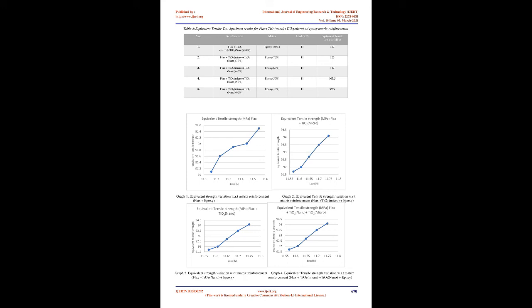From the above outcomes we can see that the highest tensile strength is obtained at Flax plus TiO2 micro plus TiO2 nano, 20%, and epoxy, 80%, composition. Concluding remarks. The tensile strength of all 6 samples was evaluated and test results of all samples are shown in the table. It was discovered that sample 1 has the lowest ultimate tensile strength when compared with the remaining samples. Then after there was a tremendous increase in ultimate tensile strength for samples 2 and 3.